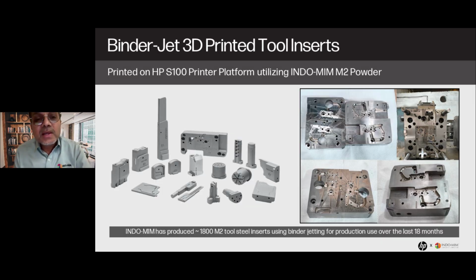So these are some examples of the mold elements, just for your reference. We printed mold elements as small as 300 grams, but we also printed mold elements as heavy as 10 to 12 kilos. Some of the mold cavities you see in the picture here are easily around 8 to 10 kilos, which is quite surprising for the 3D printing industry, where with LPBF, especially in the mid-level situation, you don't really print more than 4 or 5 kilos of material.